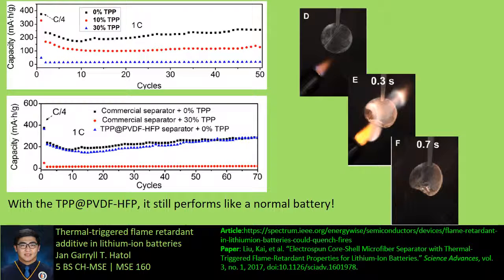So what makes this separator special is illustrated on the images shown on the chart. The top left image shows directly mixing TPP with electrolyte and its negative effect on capacity, which shows that more TPP equals less battery capacity. The bottom left image shows no direct mixing of TPP, the black line, versus 30% directly mixed TPP, the red line, versus the thermal triggered flame retardant separator, which is the blue line.